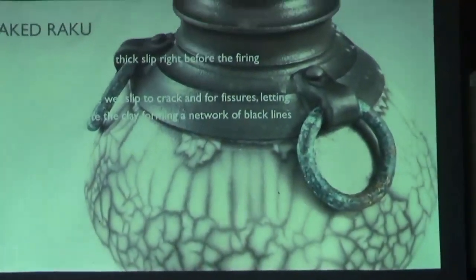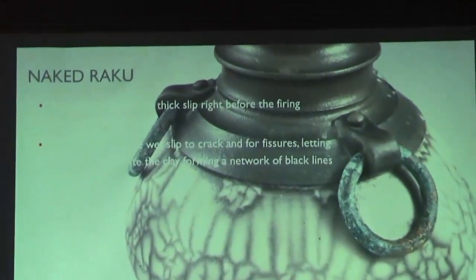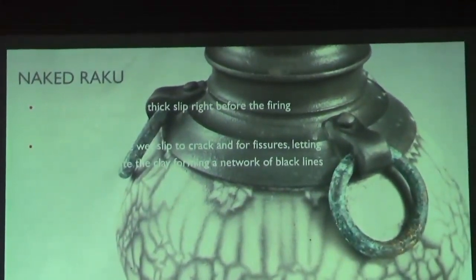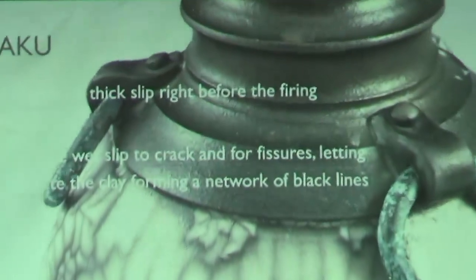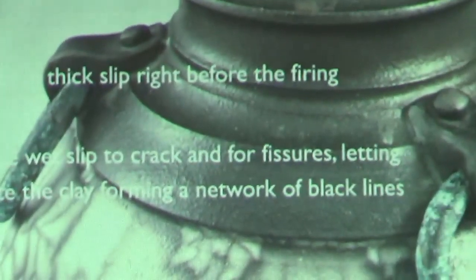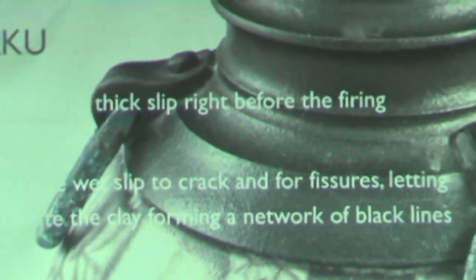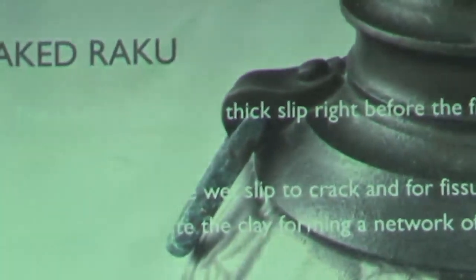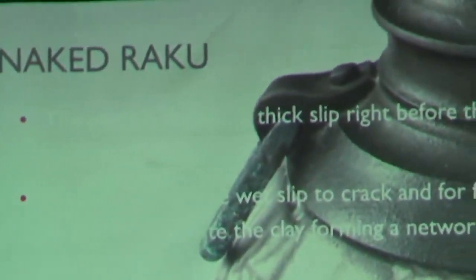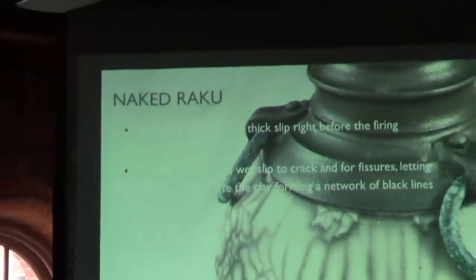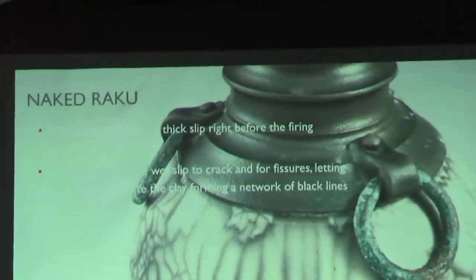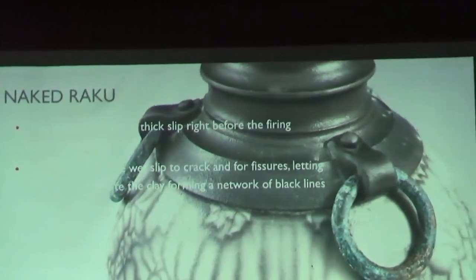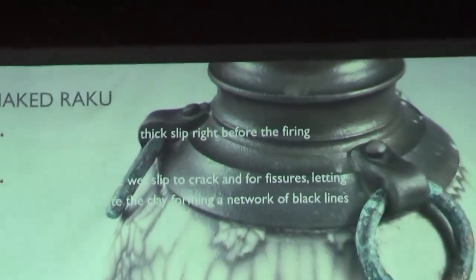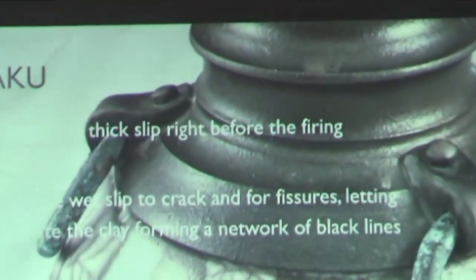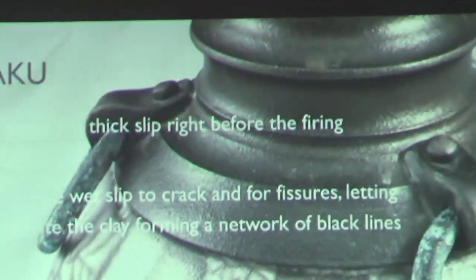Okay, so this says on my screen, it's a lot easier to see. Naked raku, and the piece in question, where at least it's exposed, is doused in a thick slip, and it's a very specific formula that has to get played with, at least the ratios, to get just right for it to crack but not fall off the piece. But to crack enough where it lets the pattern come through. It's a little bit of trial and error, but once you get it, it's so sweet. So it's doused in this thick slip. It's the consistency of pancake batter, right before going into the kiln.